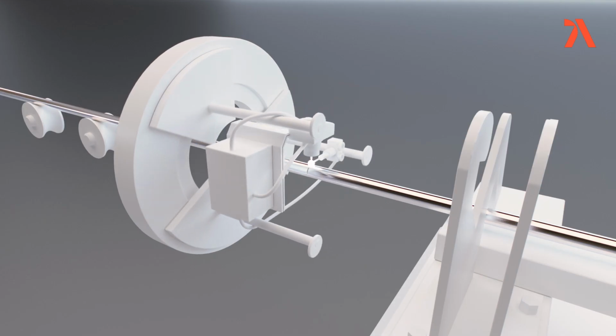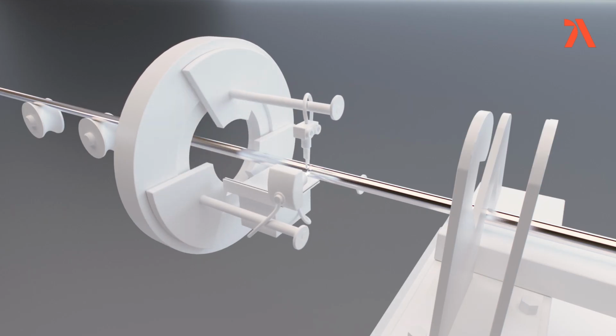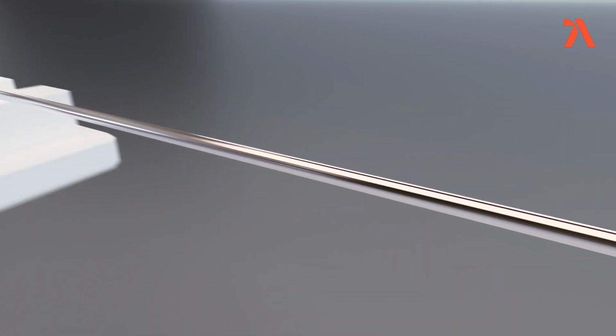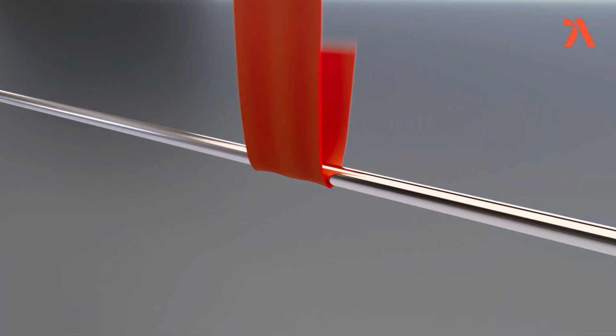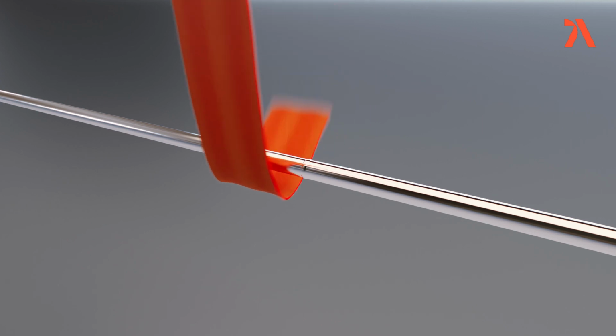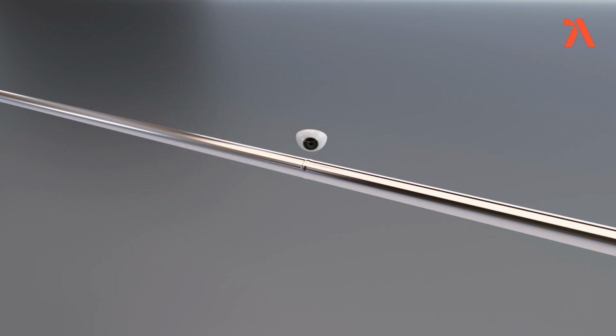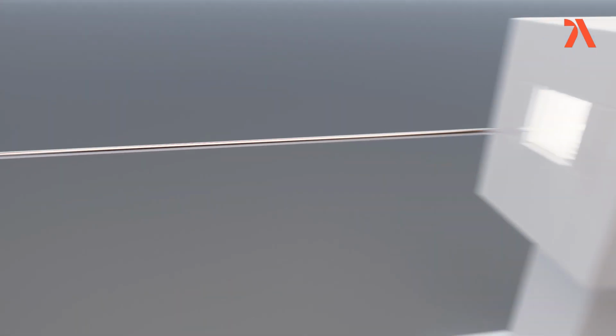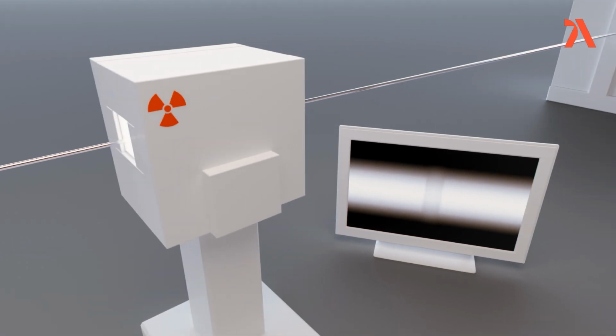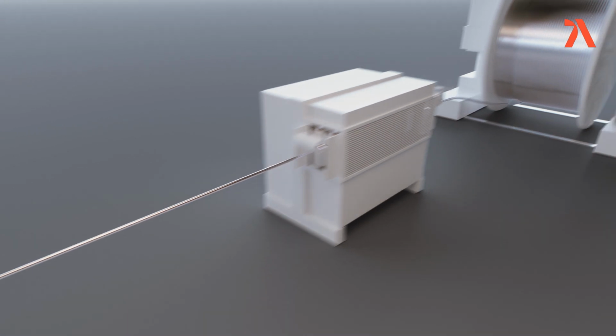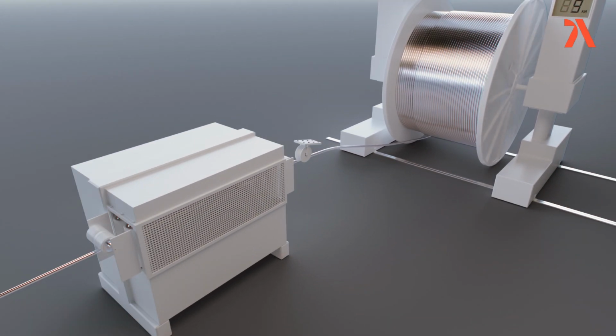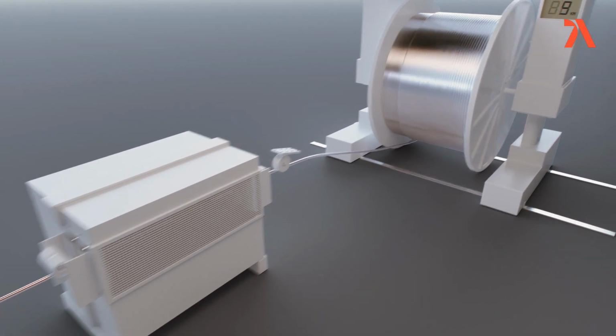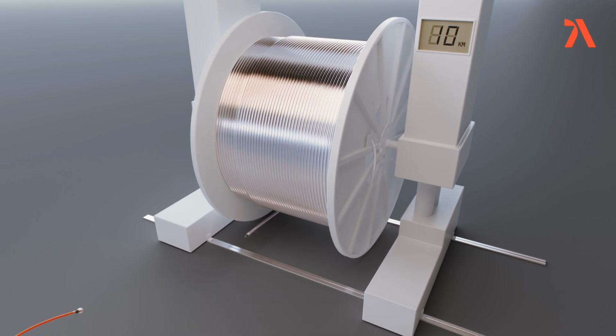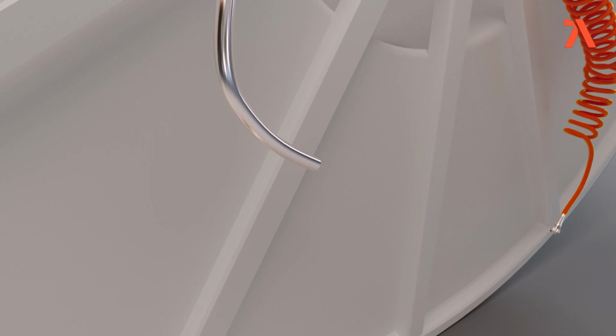The tubes are orbitally welded to meet the desired length of umbilical applications. A matching filler metal is used to ensure the highest strength and corrosion properties in the joint. Since Alleima produces longer length tubes than anyone else, the number of joints can be kept to a minimum. The joints are carefully X-rayed to detect any defects. The welded tube is then coiled on drums. One coil can hold as much as 30,000 meters of tube.